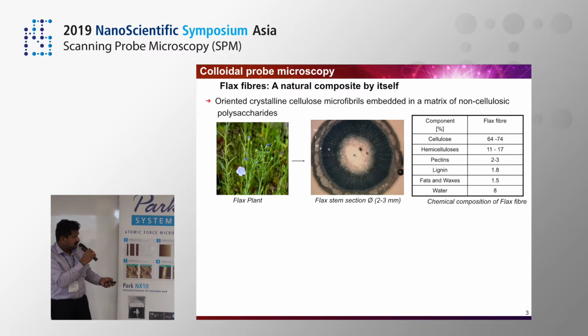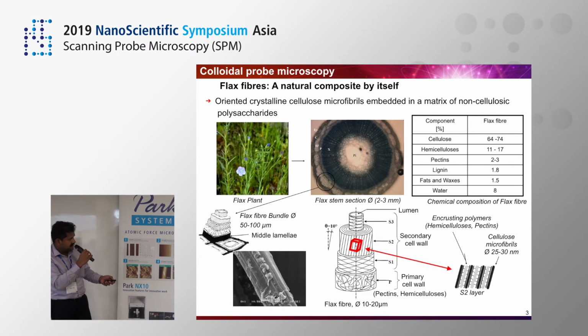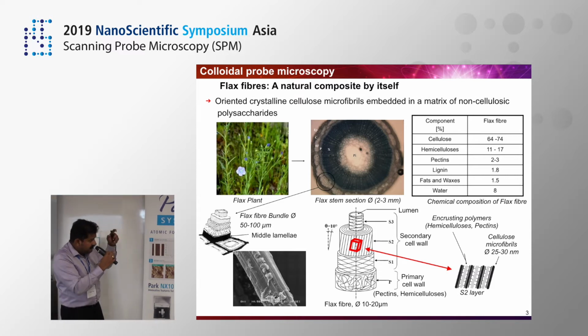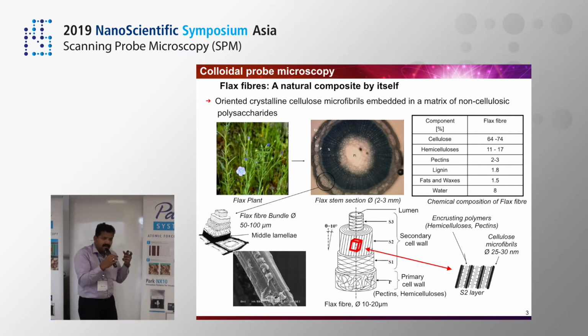And this is a cross-section of this flax plant, and these fibers appear as bundles close to the stem. And here is an SEM image of a single flax fiber, which is around 20 micrometer in diameter. If you see the structure of this flax fiber, this itself is a composite material, comprising mainly a primary cell wall and a secondary cell wall. The primary cell wall consists of pectins and hemicellulose polysaccharides, and it's a thin layer, while the secondary layer consists of highly oriented cellulose microfibers. And these cellulose microfibers are highly crystalline, and they are embedded in what is called encrusting polymers composed of hemicellulose and pectins. So that is the load-bearing component of the fiber, which gives them this high specific strength.